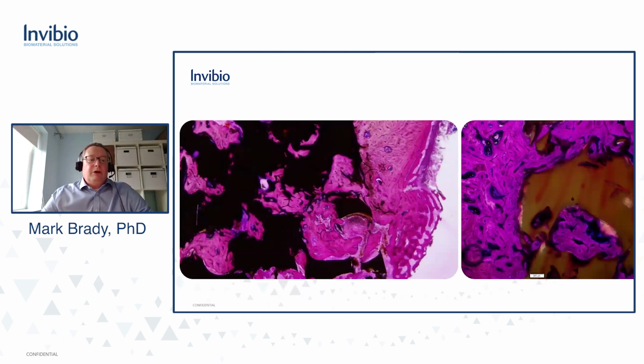And we can see in some of the non-additive manufactured porous studies that we've done in the past, with bone growing right into the porous features in this long bone study that we performed with Bill Walsh some number of years ago now. And this is as early as 4 weeks after implantation. And whilst we haven't got 100% continuous contact between the PEEK and the bone, there are areas of intimate contact between the bone and the PEEK with no intervening fibrous tissues.